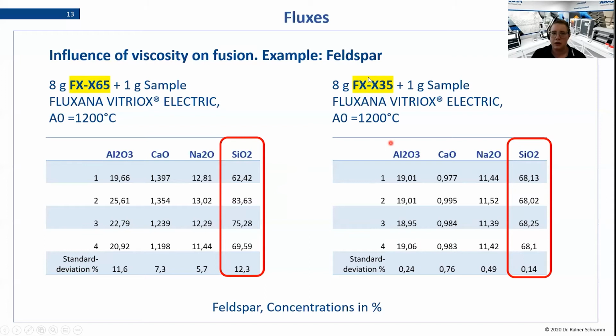So then we exchanged the flux, and what we see here is the influence the viscosity has on the fusion. We have a lower viscosity, now we can agitate properly, everything is dissolved, and we get a very nice standard deviation here, very nice precision in the same sample, using the same machine, at the same temperature, with all parameters the same, but a way better outcome here.